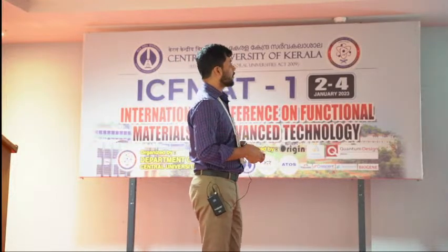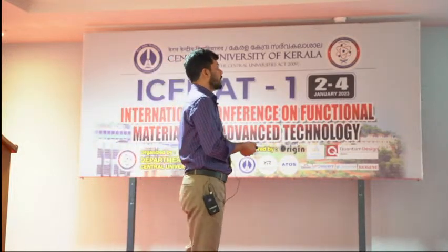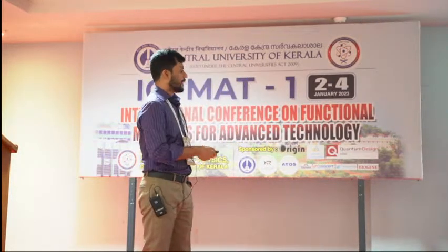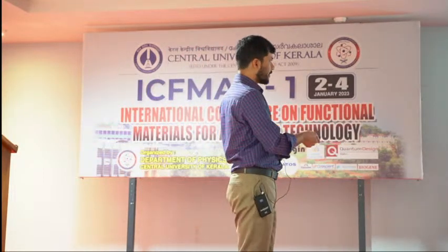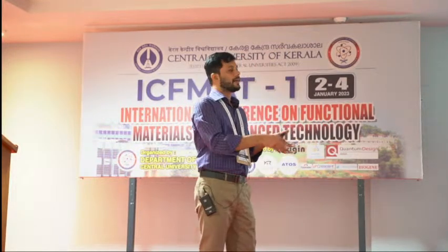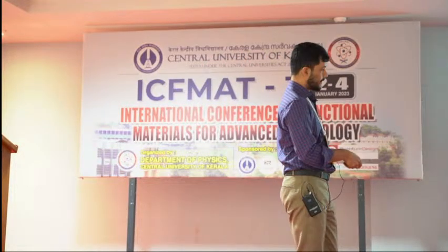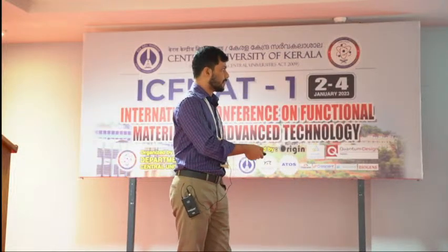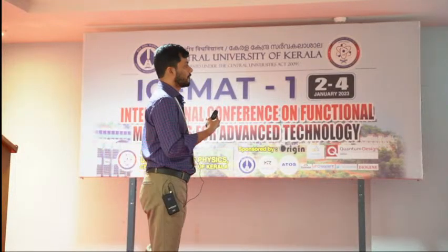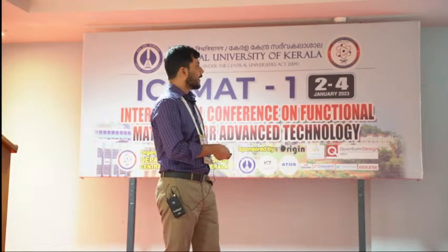And this is what we did. We fabricated silver nanowires, or silver nanorods, which have an aspect ratio between 10 and 17, which falls well within the optimized range. We used these together with rhodamine 6G. We took rhodamine 6G, put these nanoscatterers in there, and pumped the solution with a nanosecond laser, and this generates random laser emission from this particular sample. This is the actual picture of the sample being pumped by a 532 nanometer nanosecond laser.